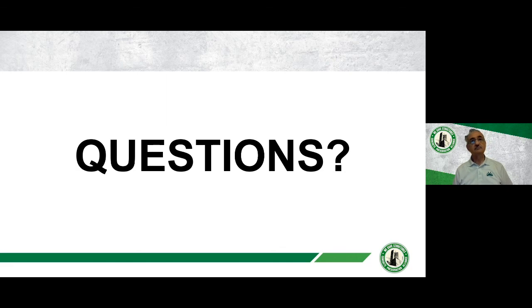Another question was related to the use of the high pH as an activator for the covering around the anode. Is that causing any issues to the concrete itself, or in particular related to alkali silica reactivity? Okay, I've written it down, but I've not mentioned it: one of the main reasons we use lithium hydroxide instead of any of the other alkalis is because lithium ions actually inhibit alkali-silica reaction. So irrespective of whether you're producing more alkali, the fact that you've got lithium ions there stops alkali-silica reaction anyway.